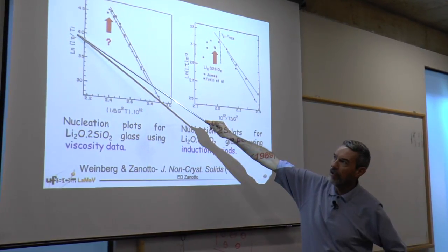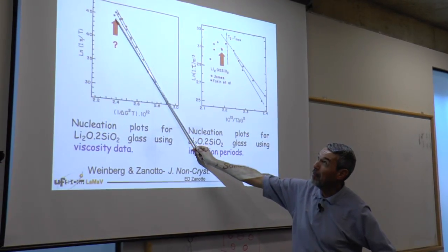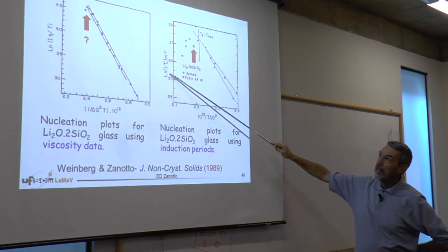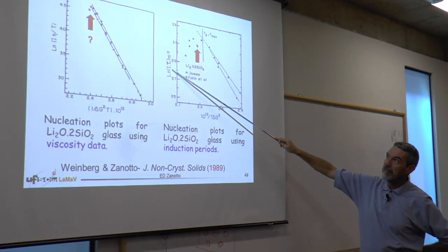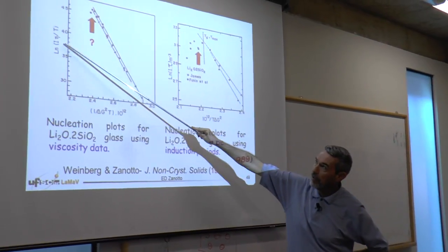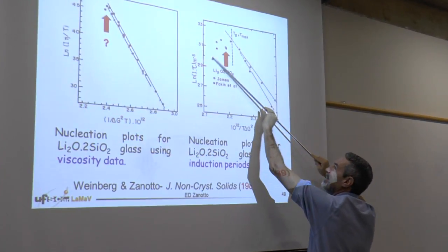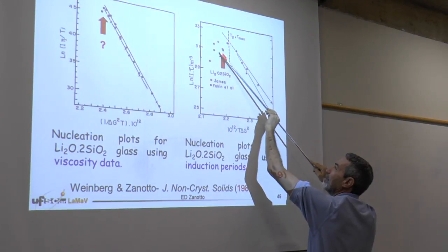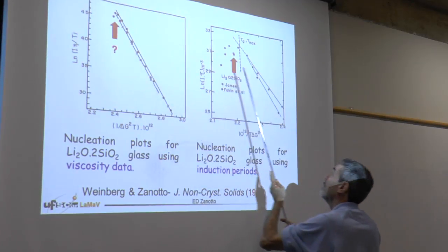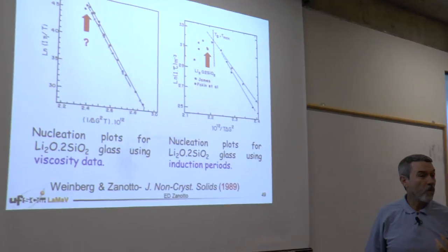rates, viscosity over T, with the good straight line, except for maybe 1 or 2 data points. Now, this is the plot for log of steady state nucleation rates times tau rather than viscosity. And then the agreement is even worse. You see, here is okay, except perhaps for one data point. If you look here, the agreement is even worse.